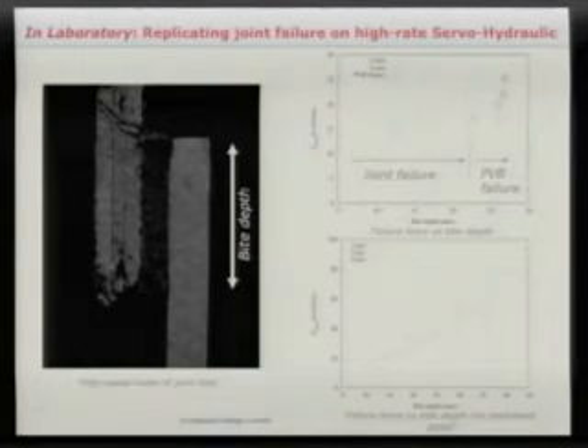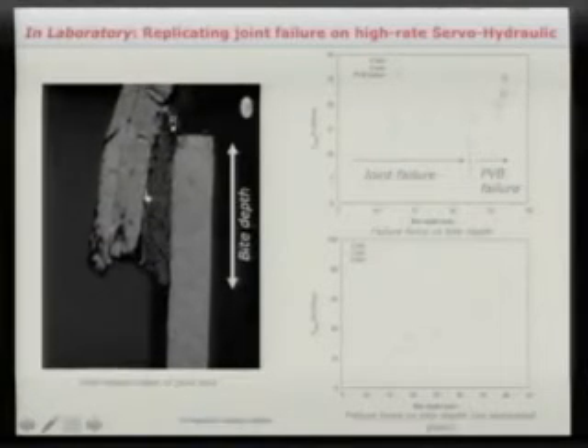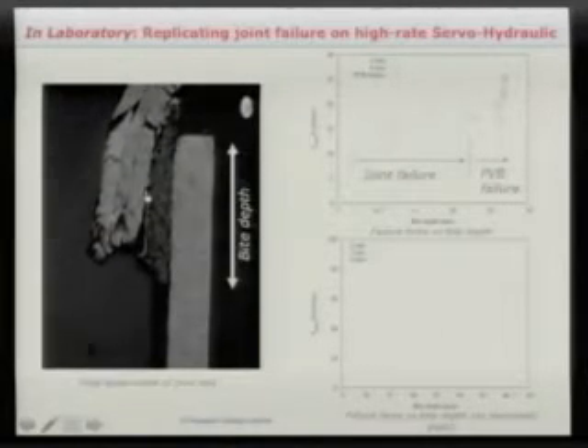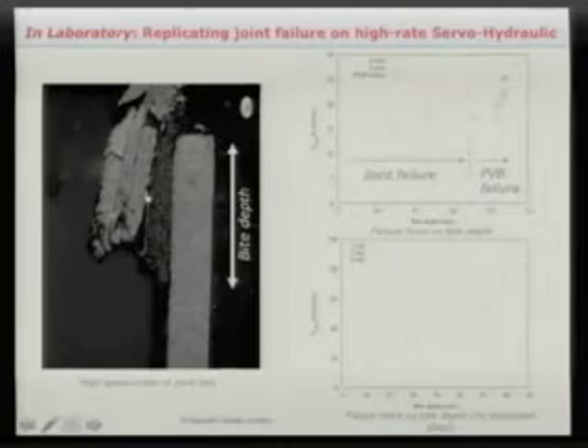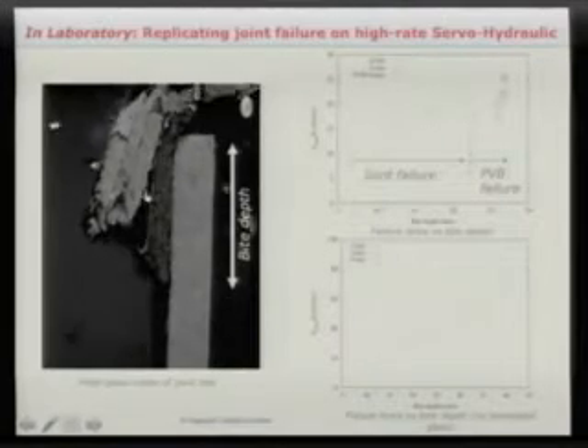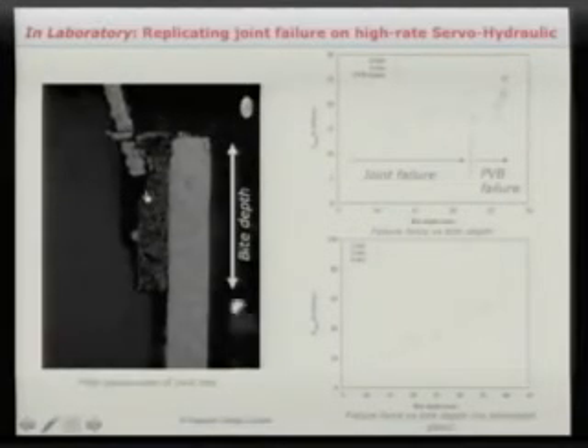So here you're looking at the joint. This is the aluminium frame of your window. Here is the silicone sealant. And this is the laminated glass sheet. You can see the PVB there down the centre. So I'm going to play this and you'll see the laminated glass sheet being pulled at several metres per second, which simulates the blast condition. The PVB is stretching and then it separates away.